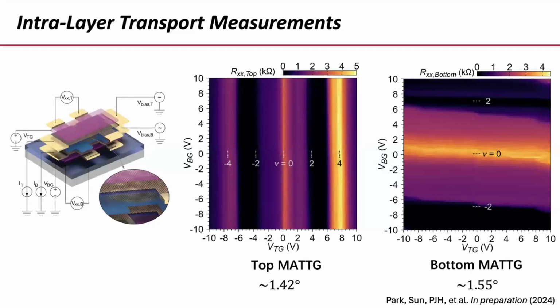So, the resistivity as a function of back gate and top gate. This is the resistivity of the top layer. That's why these features are mostly vertical. In reality, there's a little bit of an angle, but it's mostly vertical because the bottom magic angle tri-layer screens the back gate. So this is why you have insulating peaks near nu equals 0, nu equals plus minus 4, and superconductivity for 2 electrons or holes per moiré unit cell plus extra doping. That's what you expect.